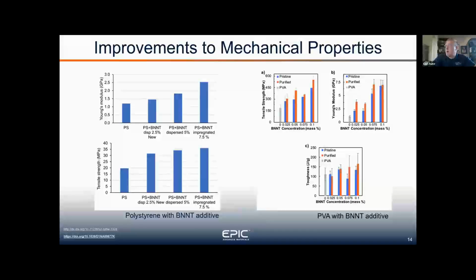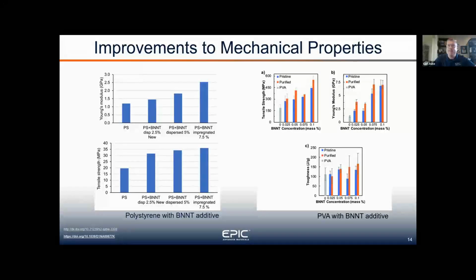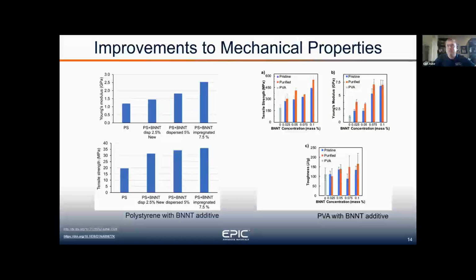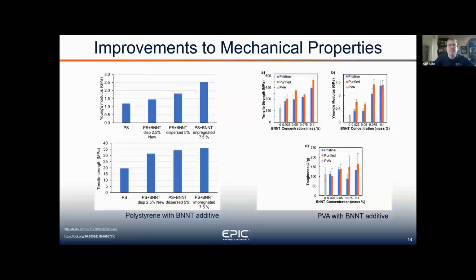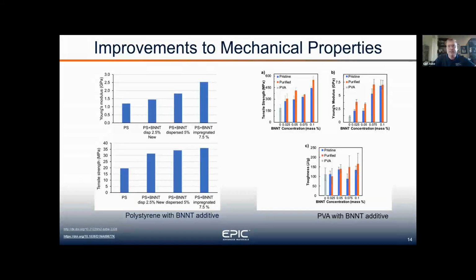So in mechanical properties, I just want to show a couple examples. Here's a polystyrene and a PVA, where adding the BNNTs improves Young's modulus and tensile strength. Each resin system incorporates these BNNTs differently, and the results are different. Sometimes you require half a weight percent of material, sometimes all the way up to 5 weight percent of material, depending on the resin system and the results desired.